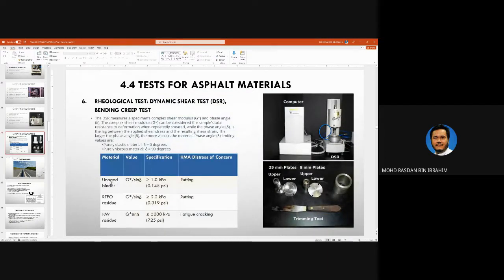So for an unaged binder, it must have the value of more than 1 kPa. And then here, this is RTFO residue and PAV residue, meaning that you take the fresh bitumen, subject it to this machine, the rolling thin film oven machine, and the next sample you put it in the pressure aging vessel machine. So for the RTFO machine, the value is more than 2.2 kPa, then we can say that it is good to resist rutting. So you need to have a combination between unaged binder and aged binder, test it and make sure that for the unaged it is more than 1.0 kPa, for RTFO more than 2.2. So you can say that it is good for resisting rutting.